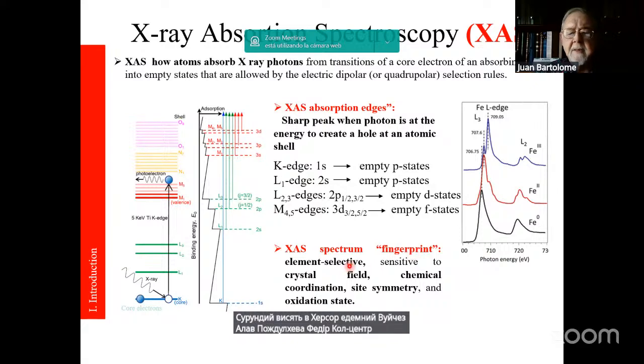So it is element selective, but it is also sensitive to the crystal field, chemical coordination, site symmetry, and oxidation state. Here we have an example on iron, the XAS of iron, where we see three cases with different valence states: 0, 2, and 3. You can see clearly that there are shifts in the edge energy and different structures that allow us to use it as a fingerprint technique.